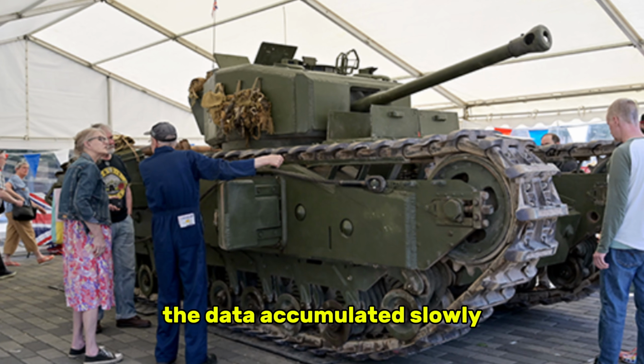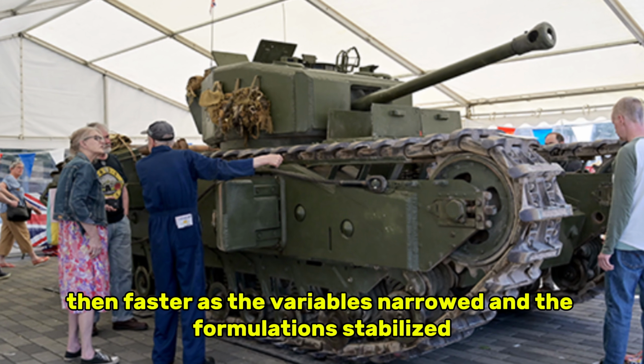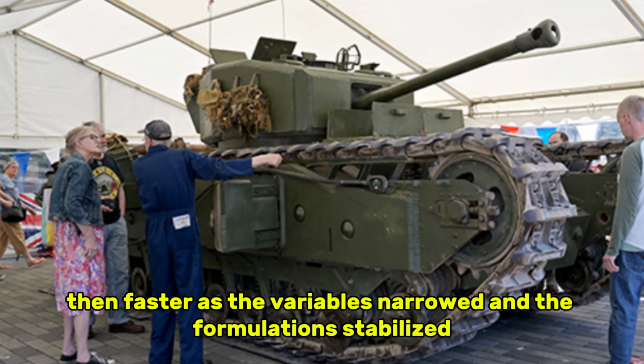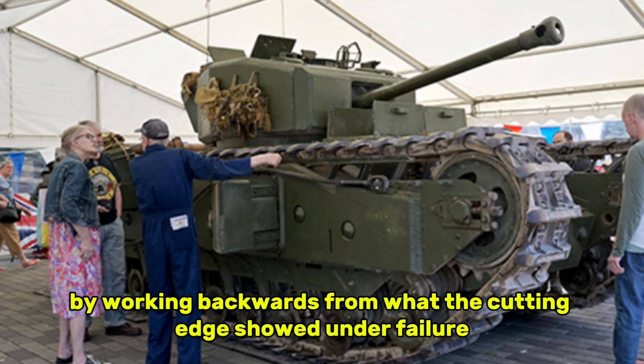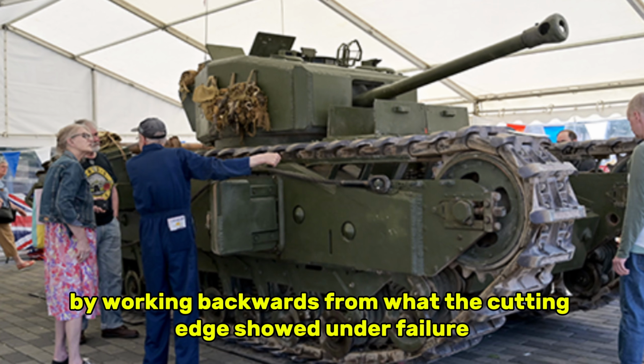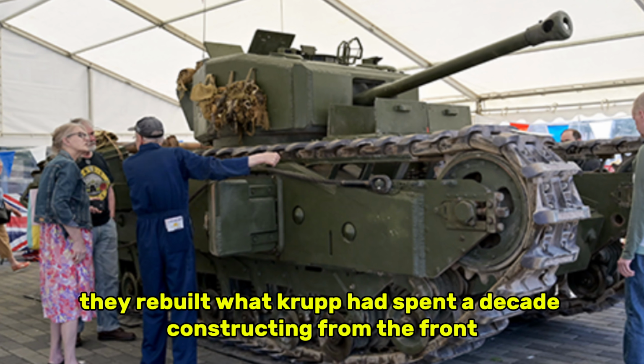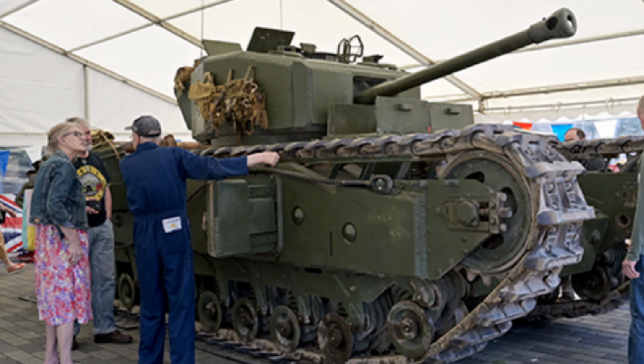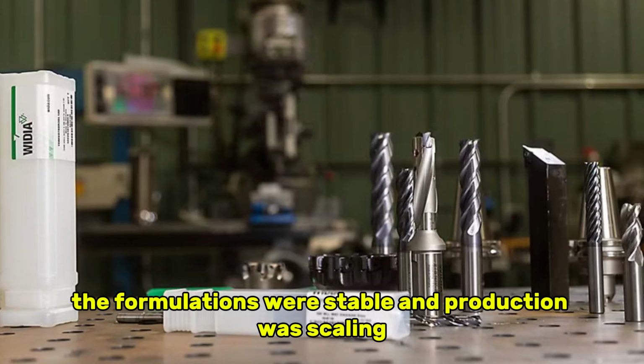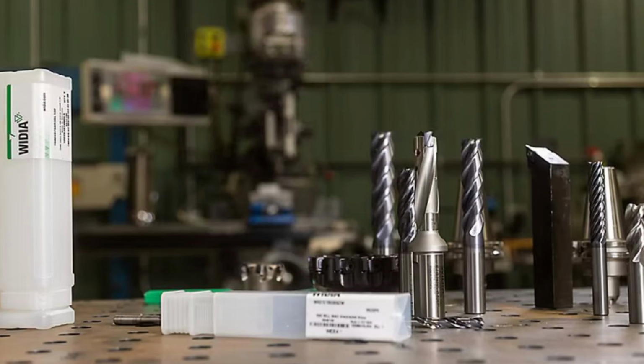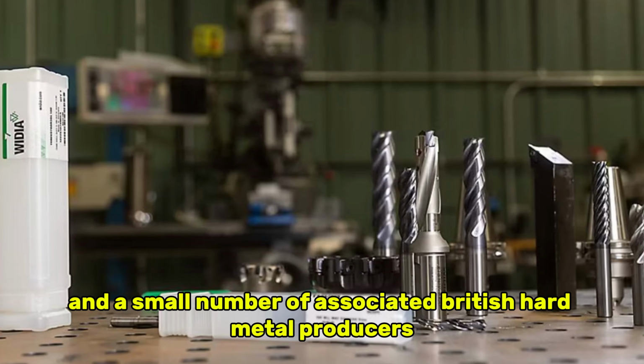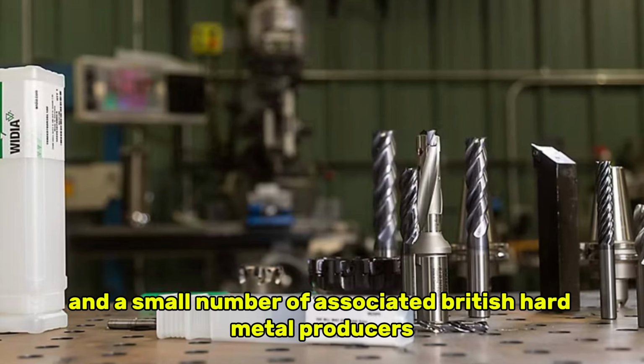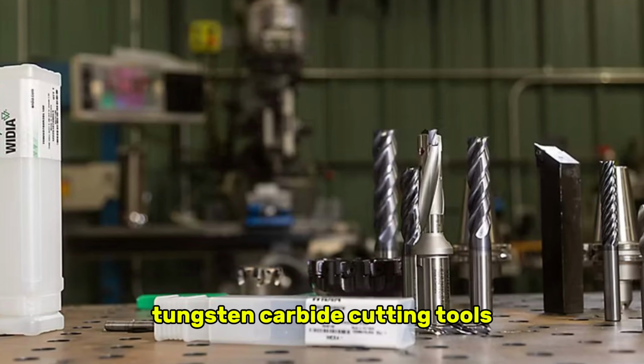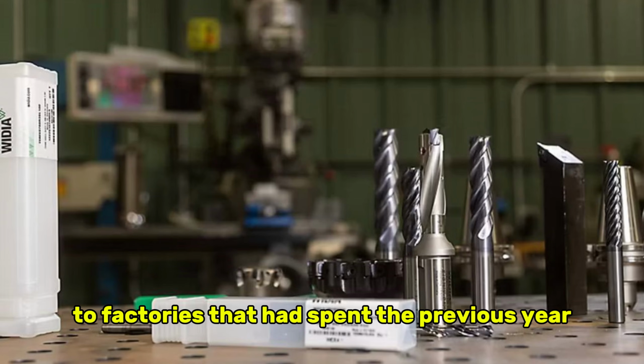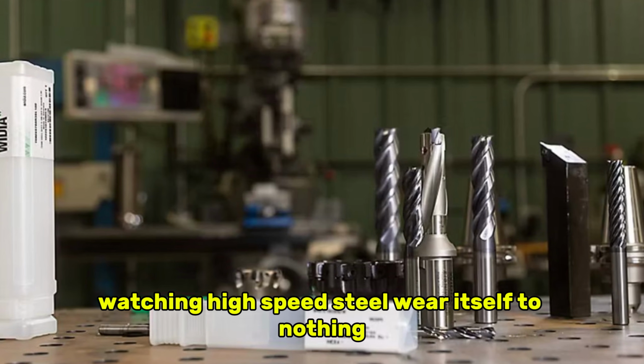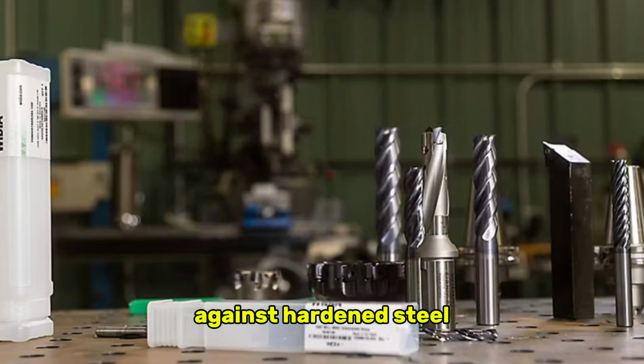The data accumulated slowly, then faster, as the variables narrowed and the formulations stabilized. By working backwards from what the cutting edge showed under failure, they rebuilt what Krupp had spent a decade constructing from the front. By 1943, the formulations were stable and production was scaling. Metro-Vickers and a small number of associated British hard metal producers were supplying domestically developed tungsten carbide cutting tools to factories that had spent the previous year watching high-speed steel wear itself to nothing against hardened steel.